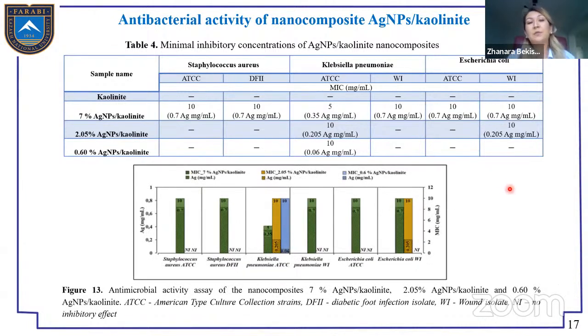The antibacterial activity of the nanocomposite based on kaolinite with silver nanoparticles was studied against 6 strains. These were from the American Type Culture Collection and wound isolates from diabetic infections. The composite with 7% of silver nanoparticles shows antibacterial efficiency against all bacteria, but the second composite acted only against Klebsiella pneumoniae and Escherichia coli, and the one containing 0.6% acted against Klebsiella pneumoniae from the American Type Culture Collection.